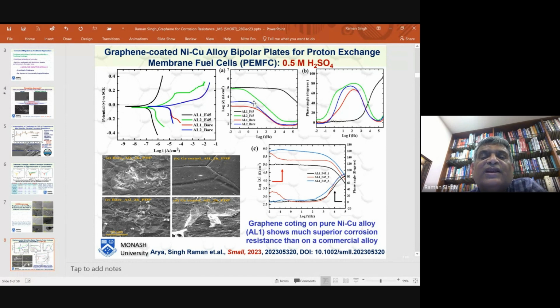This is what is called electrochemical impedance spectroscopy plots, where again the impedance value at the lowest frequency gives me corrosion resistance. And this is unique behavior for this particular material, that over a large spectrum of frequency, there is no change in impedance. This is the first time we saw behavior like this. And as you can see, graphene coated pristine nickel copper alloy does not undergo much corrosion at all. But if you didn't use the proper alloy, the graphene starts to get disrupted, and that's why behavior is not as good, this green plot. Okay.